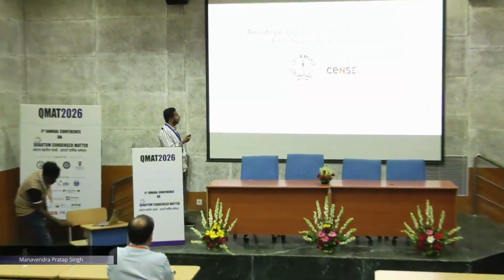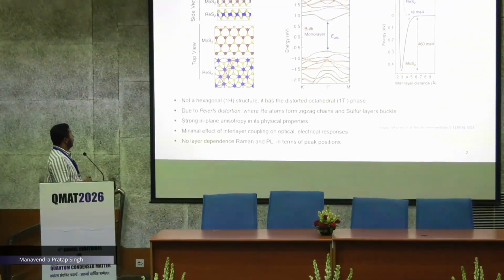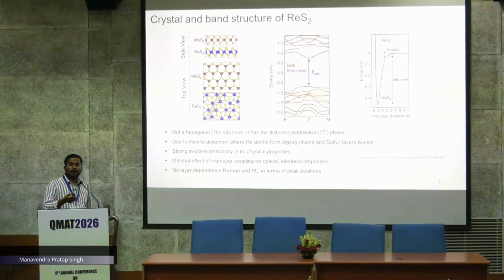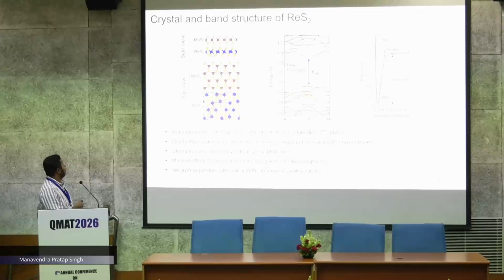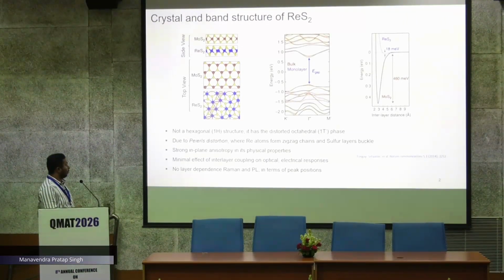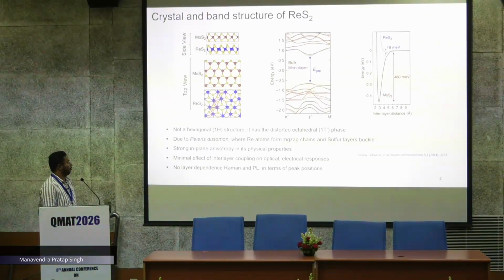So in continuation of the talk series in this session, I think my work is also aligning in that way. The title is Anisotropic in-plane thermal conductivity of freestanding few-layer ReS2, and I am from the Department of Physics, IISc Bangalore. If we talk about the ReS2 crystal structure and band structure, it is very different from other 2D TMD materials. If we compare with MoS2, it does not have a hexagonal 1H structure, but has a distorted octahedral structure due to the Peierls distortion in the Re atom zigzag chain we can see here, and due to this it has good anisotropic properties in its physical properties. We can see here that, due to that effect, there is a minimal effect of interlayer coupling in its optical and electrical responses, and I will show you in the next slide.